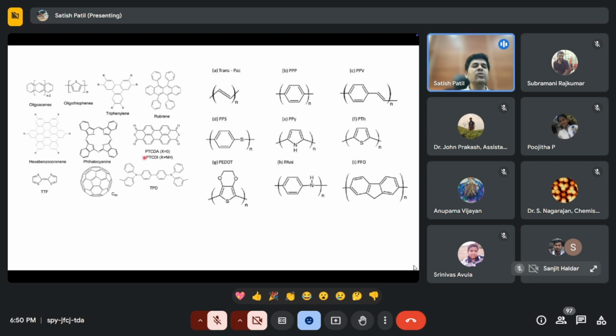Whereas in small molecules, you can grow single crystals and then you can really get rid of some of the structural disorder. So there is a difference in terms of the transport properties. For example, the charge carrier mobility of small molecules is slightly higher than polymers, because polymers contain more defects compared to small molecules. So there is a clear distinction between a small molecule and a polymer. But the beauty of this is you can tune the property.